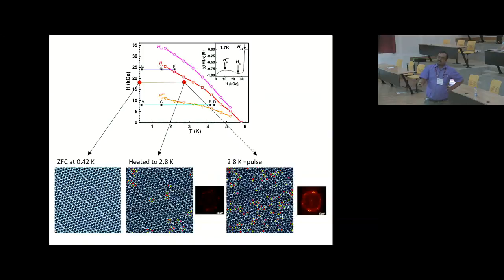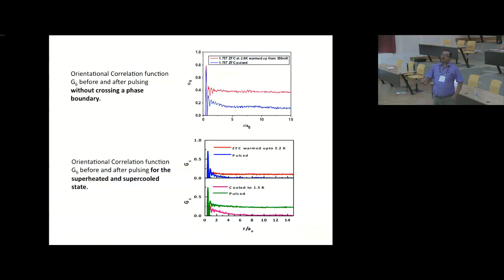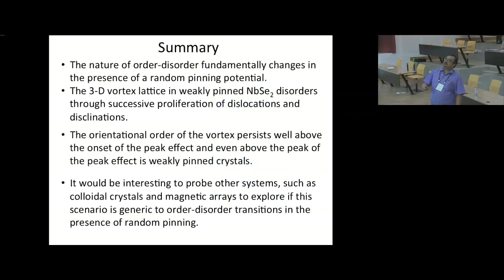But the important thing is that here the difference between this state and the pulsed state is only numbers. I have not fundamentally altered the state. This was a long-range orientational ordered state. It remains a long-range orientational ordered state. On the other hand, in this case of superheating and supercooling, the symmetry has changed. One was a long-range orientational ordered state, the other does not have long-range orientational order. All right, I think I will stop here. So this is my conclusion, and I will be taking questions.